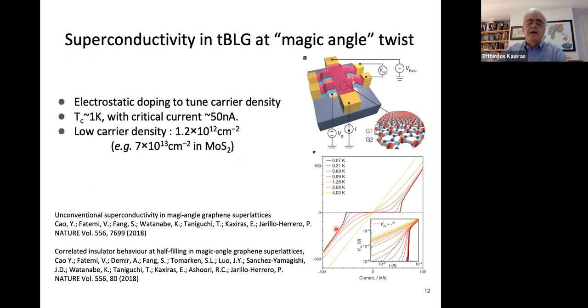The most exciting, possibly, observation was superconductivity in twisted bilayer graphene at a magic angle. Here's a picture of the device, and here are the measurements. So this is current voltage measurements showing this superconducting behavior once the temperature has fallen down to something below 1 degree. So the critical temperature is about 1 degree Kelvin, and the carrier density is quite low, about roughly two orders of magnitude smaller than typical carrier densities in semiconductors, two-dimensional semiconductors. And here are the two references which reported this very exciting discovery.